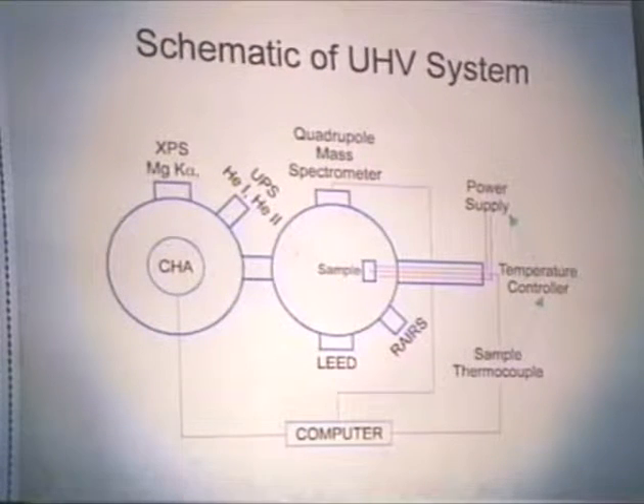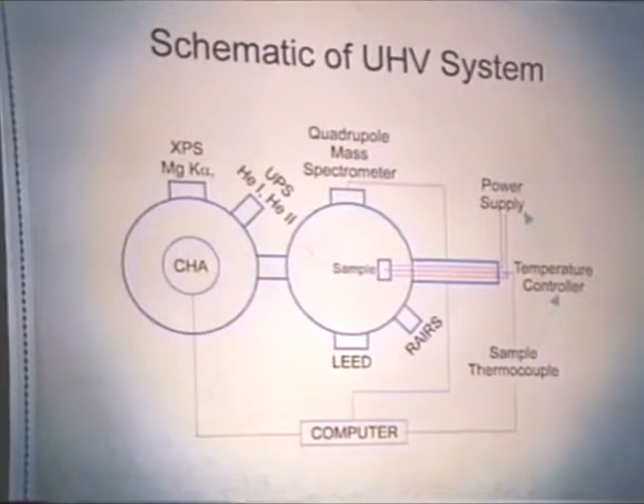The sample itself is mounted onto a tantalum sample holder. This is accomplished via tantalum shims and stainless steel screws. There's a type K thermocouple cemented directly to the back of the single crystal through a hole in the sample holder, allowing direct measurement of the sample temperature. The thermocouple is interfaced with a temperature controller and a power supply to allow heating rates to be accomplished for thermodesorption experiments.